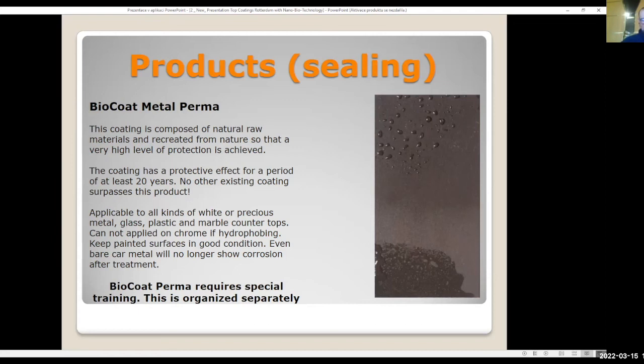Yes, this is also a very good coating for the industry. And we did, 2.5 years ago, a storage silo for glue, and it was coated with this coating to be anti-adhesive for the glue, because the cleaning made a problem. The glue was dried and hardened on the walls, and once a year it had to be taken down. And this coating has reduced the hard glue staying on the walls of the storage silo.